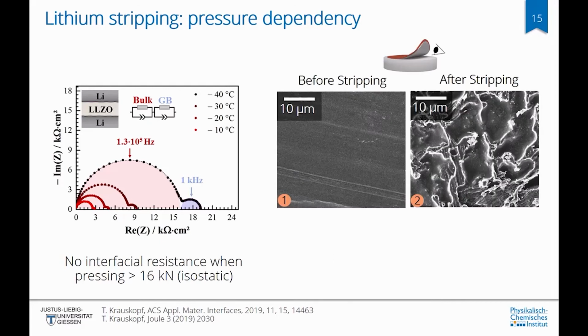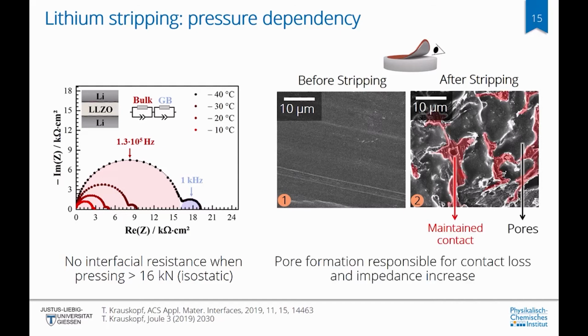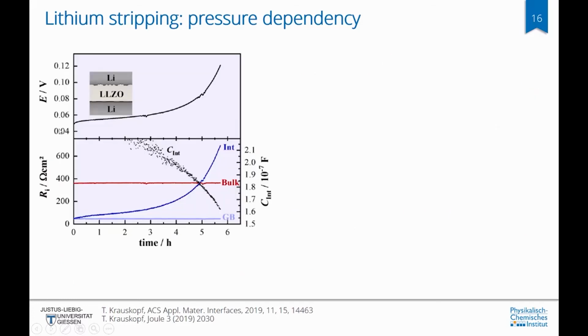However, when stripping, this interface doesn't strip evenly over the entire surface. Instead, it creates pores, and there are regions which maintain contact during stripping when comparing the SEM image after stripping to before stripping of the lithium metal. This pore formation and loss of contact is also seen in the voltage profile. As stripping time increases, more and more contact is lost, and correspondingly at a constant current, the voltage must then increase because of the interface resistance, which increases.